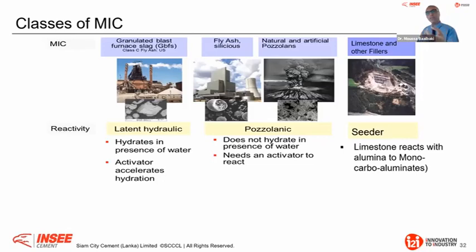And the pig iron industry is a raw material for the steel industry. It is like I produce clinker, a raw material for producing OPC or composite cement, the same. By producing pig iron in a furnace, you produce blast furnace slag. And those blast furnace slags have a basicity very often above 1. And this is why we call them not pozzolanic material, but latent hydraulic material.